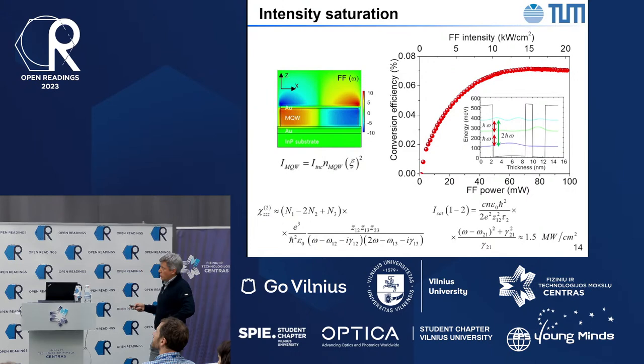This is happening because we saturate the 1 to 2 transition, from the ground state to the first excited state, which is close to the pump frequency. We purposely made it close so that we can enhance the nonlinear response, and then we slightly detuned it to reduce the saturation effects, but nevertheless, saturation effects are there. And as we saturate, we transfer electron population from the ground state to the first excited state, and if you plot the populations in the ground state, first excited state, and second excited state, the nonlinearity has this dependence on the electron population. And as we start populating the second excited state, you can see that our nonlinearity will be significantly reduced.